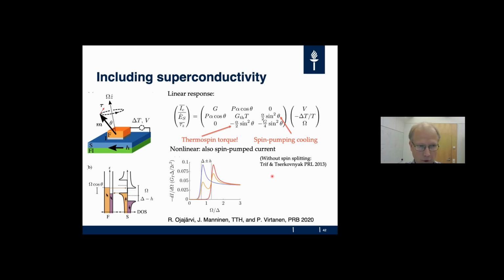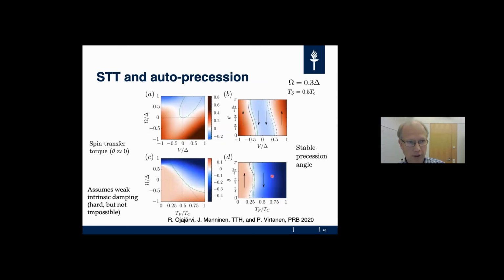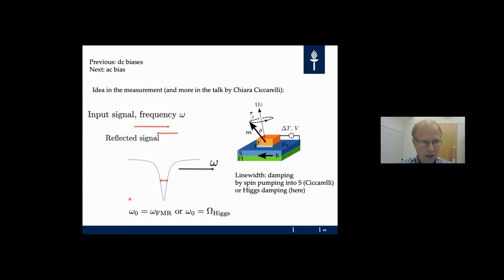One thing you can study is the possibility of auto-precession in this system. I will not go into too much detail, but we studied the possibility of, in principle, driving an auto-precession in the case of a temperature difference in the system. We found that it's in principle possible, but the problem is to overcome the intrinsic damping in these cases. We found that it's not completely impossible, so it could be done.